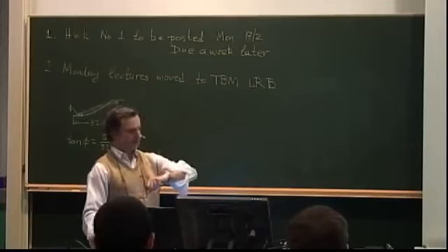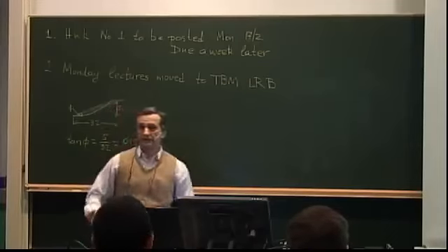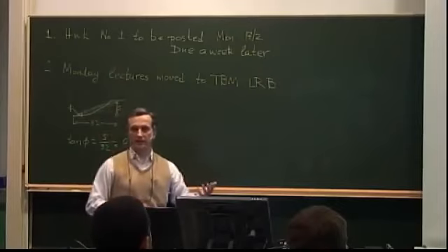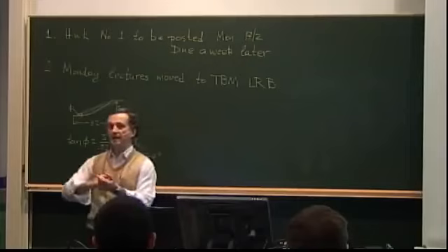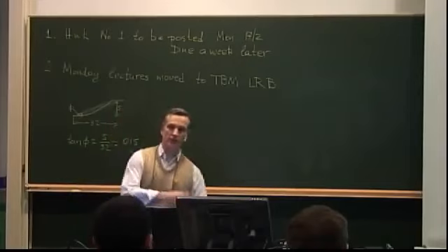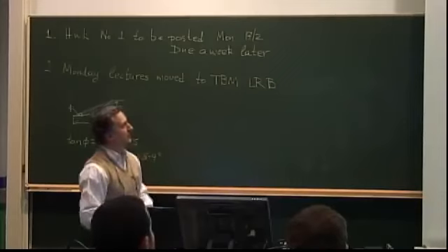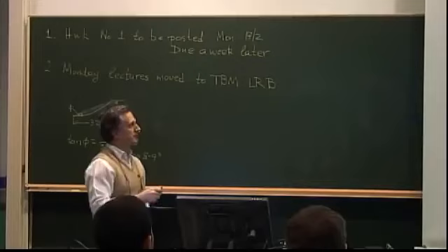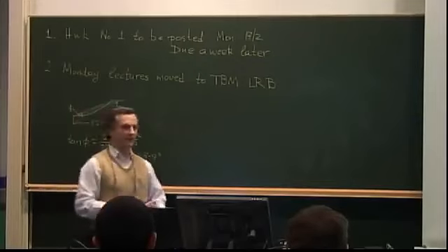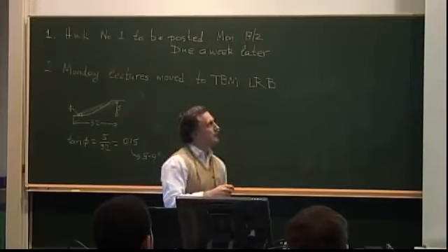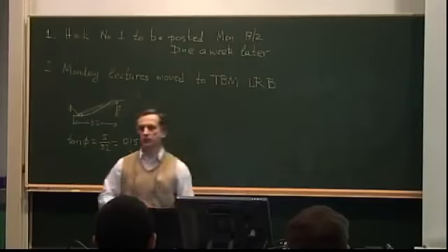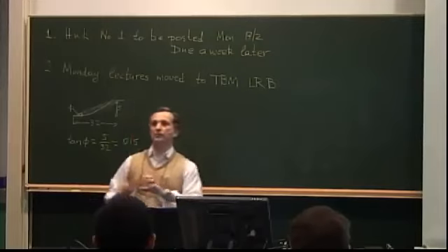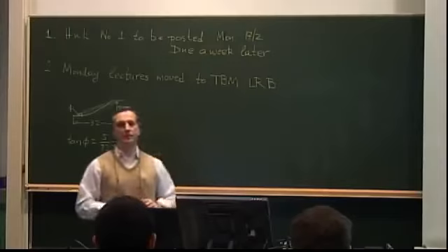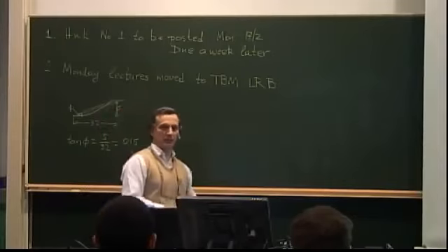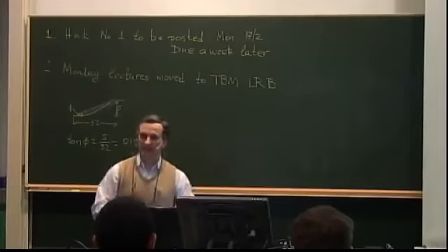So there's a maximum strain criterion, and then it starts getting interesting. People are saying, instead of using the individual ones, I recognize that somehow they combine either destructively and they cause earlier failure, or constructively and they delay failure. So Steve Tsai, now retired, a very famous person, not only for the criteria that he came up with, took a theory by a gentleman called Hill, which was developed for anisotropic metals. There was a yield theory that he developed, and he said, I will take that theory and translate it over to composites, which was the first big mistake he made, not in terms of being wrong, but in terms of exposing himself to a lot of criticism.